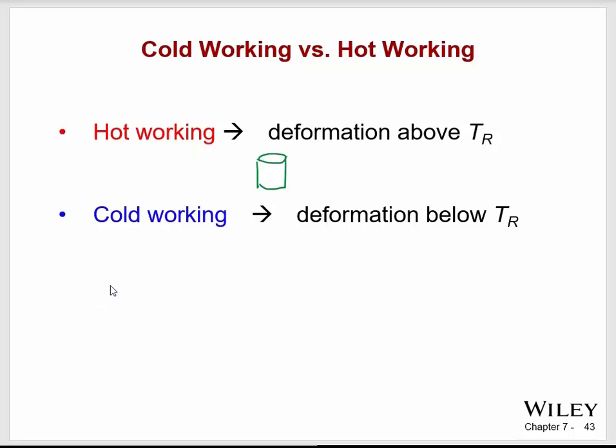There's probably some individual advantages to choosing one method over the other. For instance, a lot of the time when you elongate something through cold working, you change the orientation of the grains, and then when you restore it, even though you've restored its ductility, you can still have grains a little bit more oriented in one direction. So there are these very minute details that could be worked out from field to field about the advantages of hot working versus cold working.